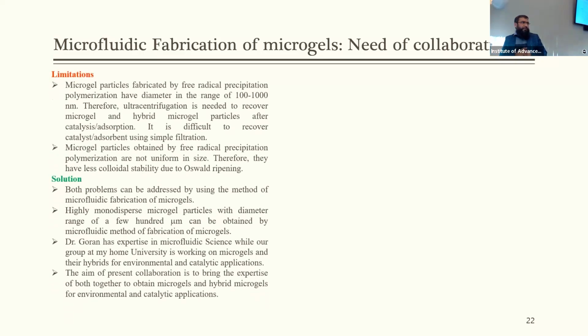The other issue with such microgel particles is the polydispersity. The particle size is not actually uniform in the case of free radical precipitation polymerization, so the system is not very stable due to polydispersity. Both of these issues can be resolved if we use microfluidic fabrication of the microgels.